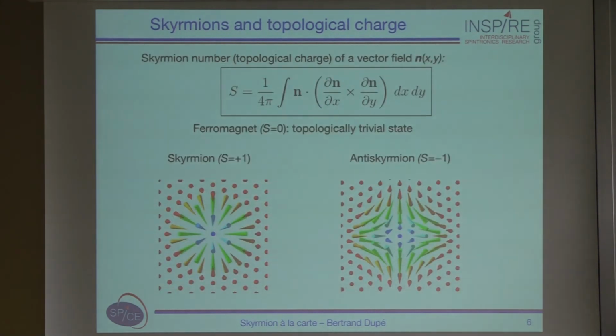In order to characterize this object, we calculate what is called the skyrmion number. We can also call it, depending on the community, the topological charge. It's a rather simple formula, which you see here. It's an integral, and it counts the number of times the magnetic moment is mapping a unit sphere as you go across the skyrmion. So you see a skyrmion here, the same picture as I've shown before, but a top view. You have a ferromagnetic background, and as you go to the center from all directions, the spins always rotate in the same direction.